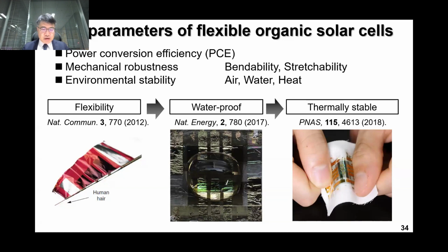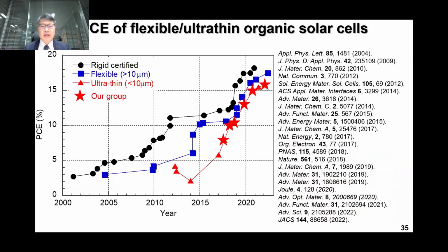With improving mechanical durability or flexibility, we then try to make a waterproof organic photovoltaic cell. And finally, we achieved a thermally stable organic photovoltaic cell. And also we improved the conversion efficiency by optimizing the process conditions or replacing the organic semiconductor with a highly efficient material. And now we achieve efficiency over 15%.